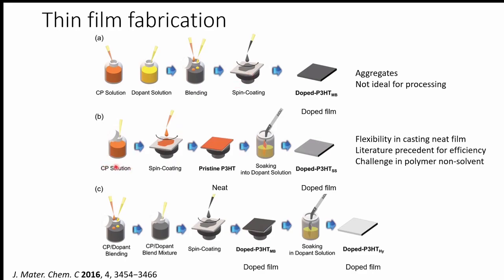Now, the other approach that you can use is, if your polymer doesn't like to behave properly, and I'll explain that in a second, you can make a neat film out of it, then you soak it in your dopant solution, and you rely on the diffusion of the dopant into your film in order to get any kind of action going on, and then you get your doped film.